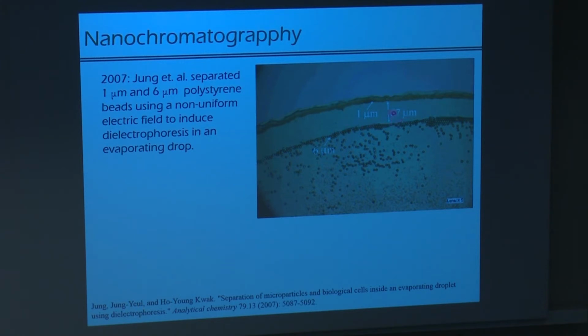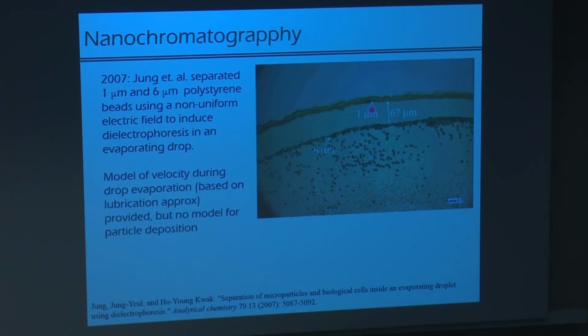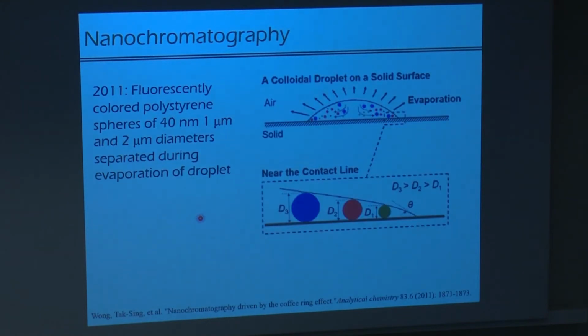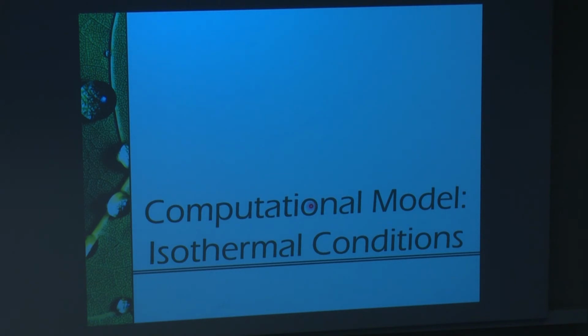Now, if you could get such nice separation just from drying a droplet, that would be interesting. So they did some modeling, but they only modeled the fluid flow. They didn't actually look at the particle deposition or anything. So we were very interested in looking at that. Another group looked at 3 different particle sizes, 40 nanometers to 2 microns in size. And once again, the smaller particles were closer to the contact line than the larger particles. So we said, well, let's do some computational modeling of this.